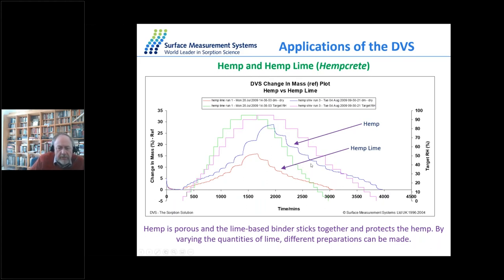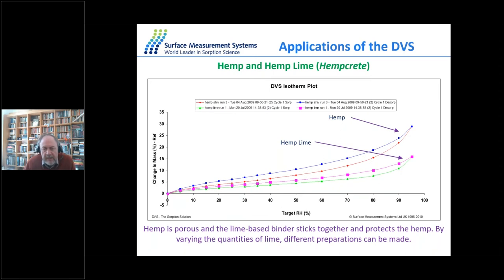And the lime-based binder, which is called hemp lime, binds together the fibers. By changing the amount of lime and hemp, you can vary the water absorption of the hemp lime. You can see this particular formulation of hemp lime actually absorbs quite a bit less water, about half the water that the hemp itself absorbs. So again, if you're trying to match compatibility of these materials, understanding how much the hemp and the hemp lime, or the hempcrete as it's called here, absorb is quite important from your design or materials perspective. And you can see from the kinetics in the previous graph, we can measure the isotherms for both the hemp and the hemp lime very easily.